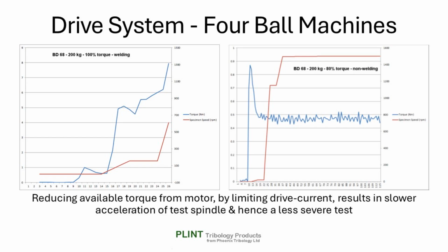torque resistance. Reducing the available torque from the motor by limiting the drive current results in much slower acceleration of the test spindle and hence a much less severe test.